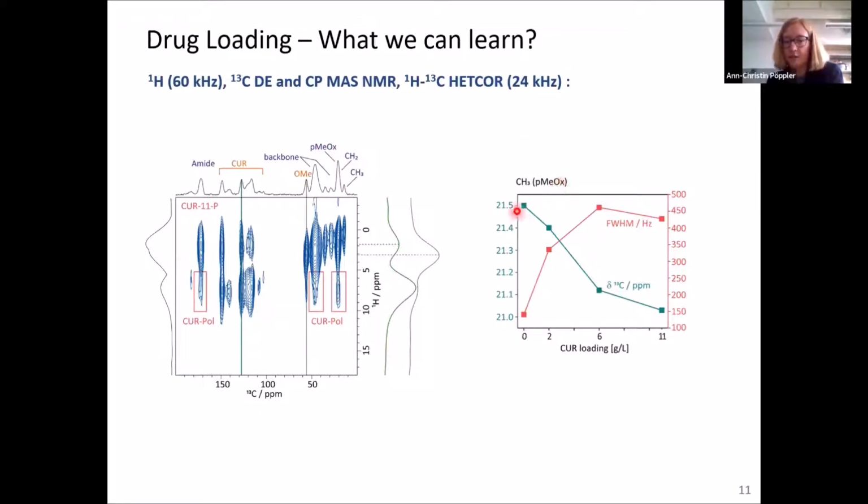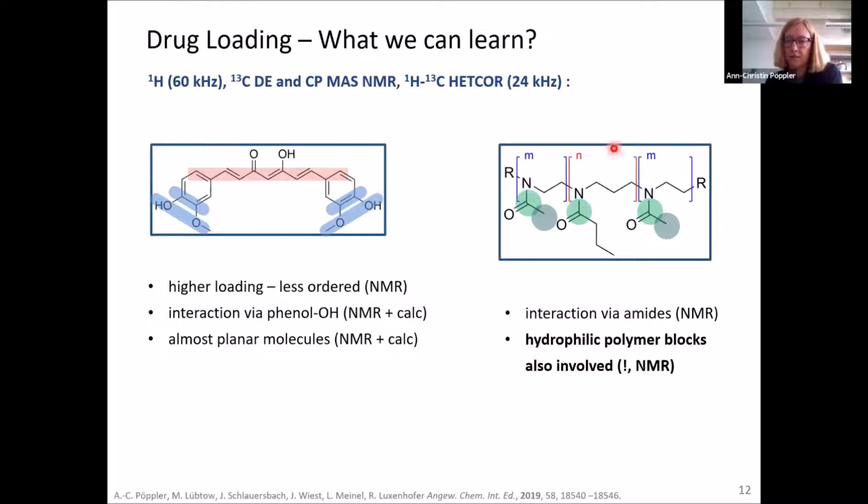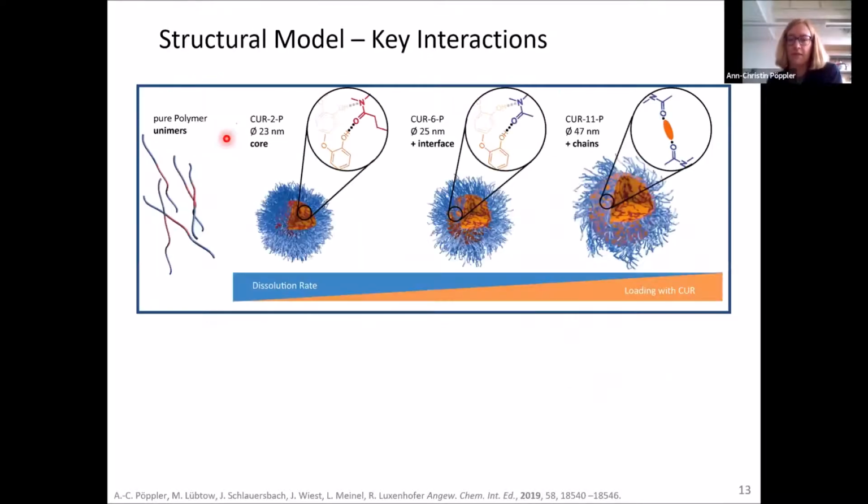And this is also mirrored by changes in the chemical shift and also changes in the full width at half maximum. And this was the first experimental indicator that not just the hydrophobic part, but also the hydrophilic part of our polymer is actually responsible for coordinating to the guest molecules. And this now gives us a possibility to explain what is happening between the different polymer-drug assemblies and the properties that we observed.